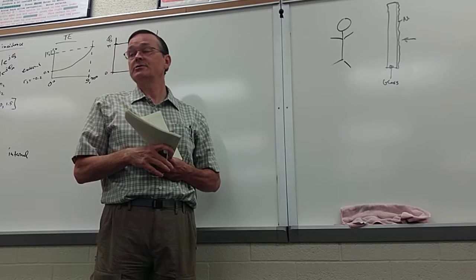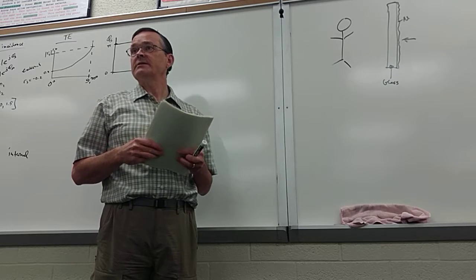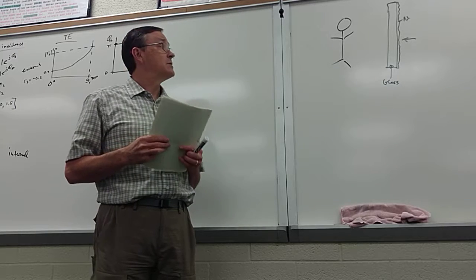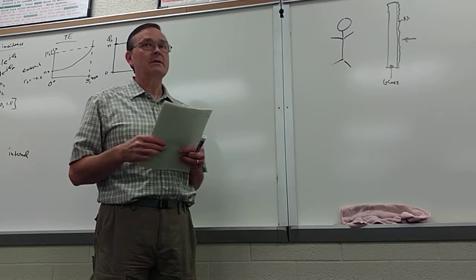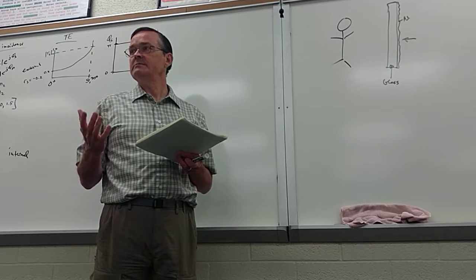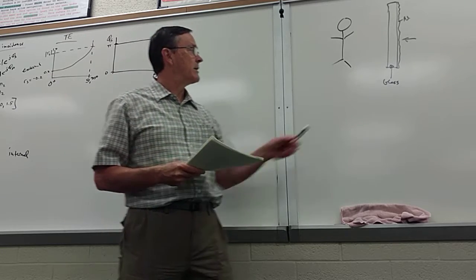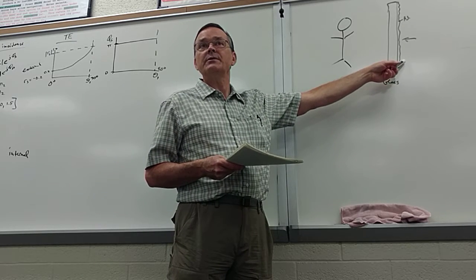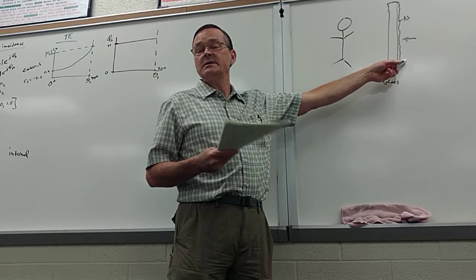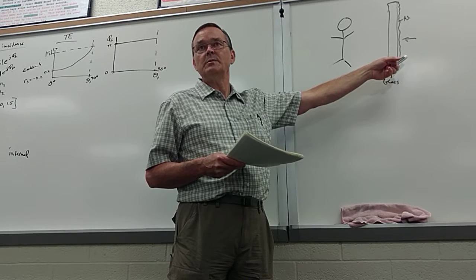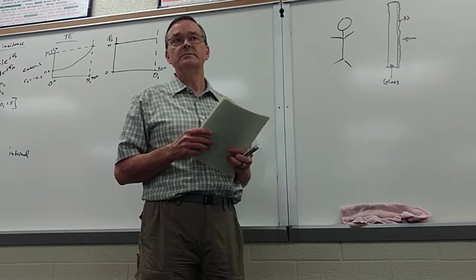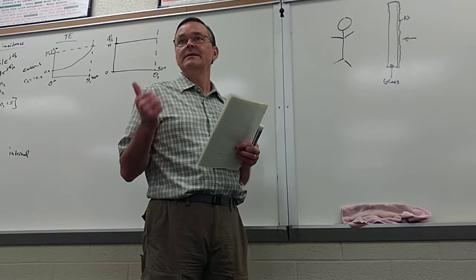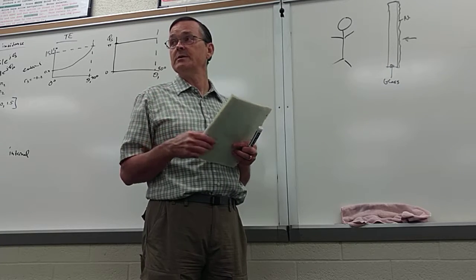It's opaque. It doesn't look very shiny. It doesn't look shiny at all. It just looks like this kind of rough metallic surface. And so basically what's happened is some aluminum, you melt it, and you just splat it onto the back of the glass, and that back surface just doesn't turn out to be very flat, and it oxidizes immediately anyway, so you get aluminum oxide covering the metal. And so it just doesn't look very mirror-like. It's not flat, and it's not actually aluminum on the surface of it, it's aluminum oxide.